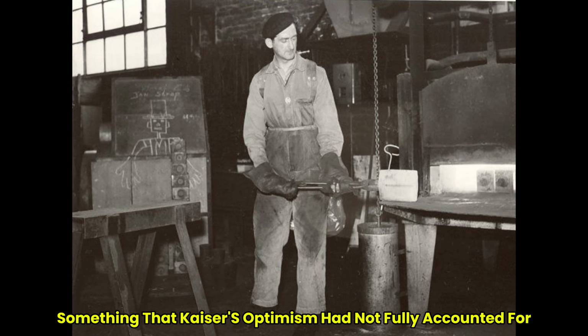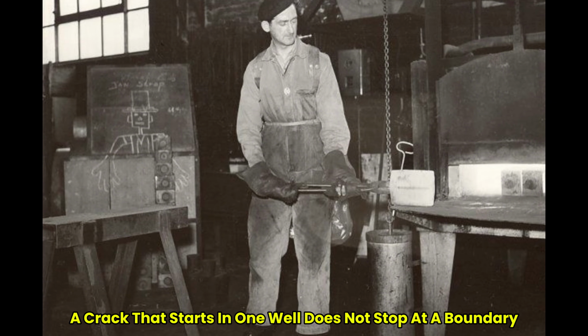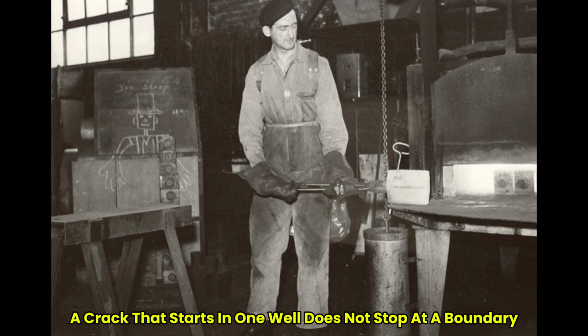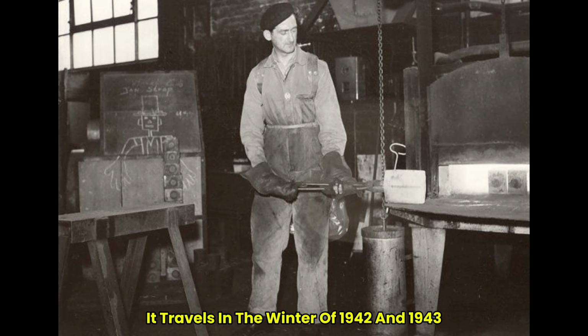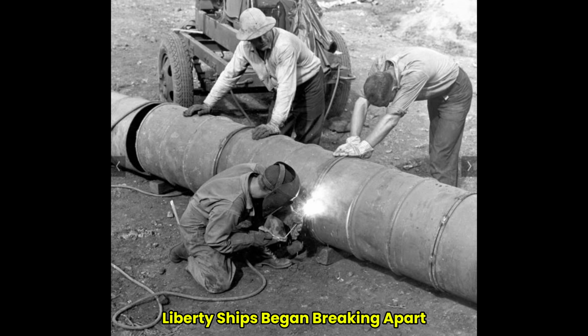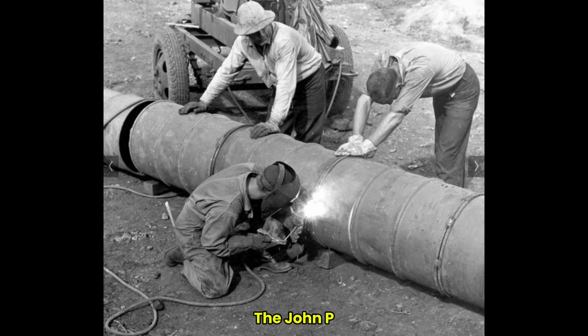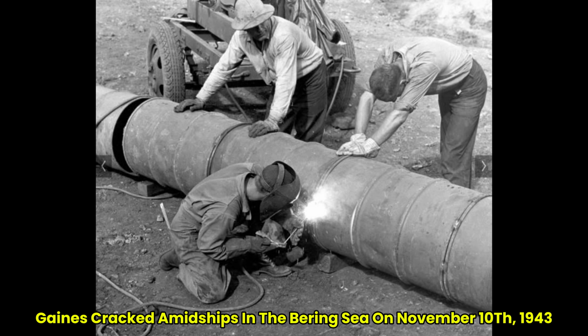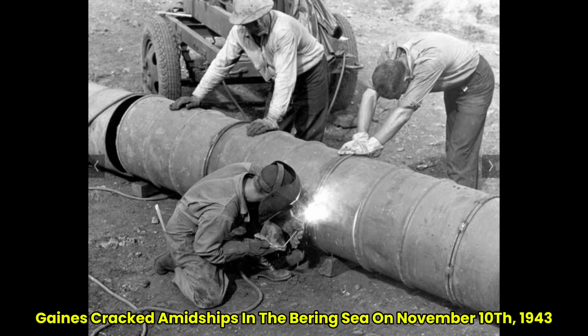Welded steel under stress cracks differently than riveted steel. In a riveted hull, when a crack propagates through one plate, it stops at the rivet holes in the boundary of that plate. The hull can fail locally without failing catastrophically. In a welded hull, the entire structure is continuous. A crack that starts in one weld does not stop at a boundary. It travels. In the winter of 1942 and 1943, Liberty ships began breaking apart. Not slowly. Suddenly. The John P. Gaines cracked amidships in the Bering Sea on November 10, 1943.